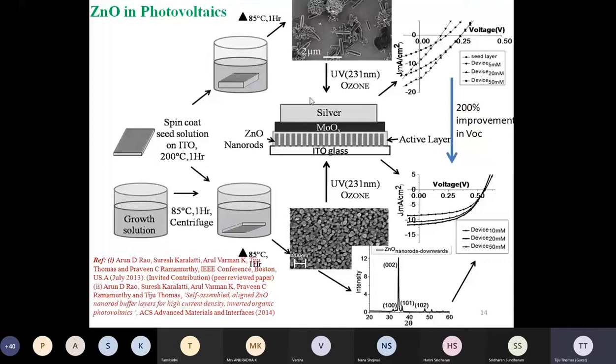And we also found that there is a variation between R star and the negative logarithm of D C naught, where D is the diffusion coefficient of a given atom in the solution, in the dispersion medium. C naught is the solubility product of the material. For example, zinc oxide, if it is made in ethanol, it is the solubility product of zinc oxide in ethanol. D would be the diffusion coefficient of zinc or oxygen in ethanol. R star would be the critical radius. So as I play with D and C naught, you see that R star becomes engineerable. I will be able to play with it.